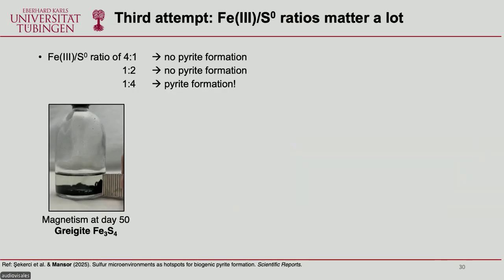Okay, that's okay. Then we can do another attempt, the third attempt. And as it turns out, we found out that iron to sulfur ratios matter a lot. We tried conditions where there's a lot of iron. We tried 1:2, which is stoichiometrically for pyrite, iron 1, sulfur 2. And then we tried 1:4, which is much higher sulfur. And then we found pyrite. So at day 50, we observed that there's already something weird going on. We can use a magnet and we can say, okay, this is when we detected greigite, which is magnetic.